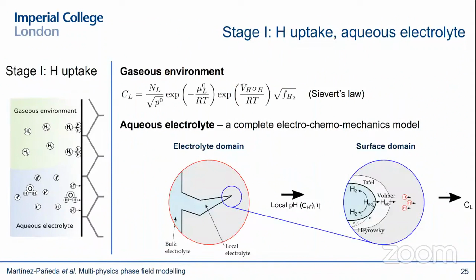So the first thing is dealing with the hydrogen uptake. So there we had to propose new models that were able to capture, quantify the absorption of hydrogen into the metal as a function of the environment. There's two typical scenarios: gaseous systems and aqueous electrolyte systems. The gaseous systems are easier, and under certain conditions, you can find an expression that relates the hydrogen pressure or fugacity to the hydrogen concentration at the metal surface.